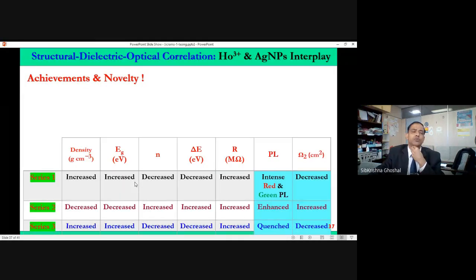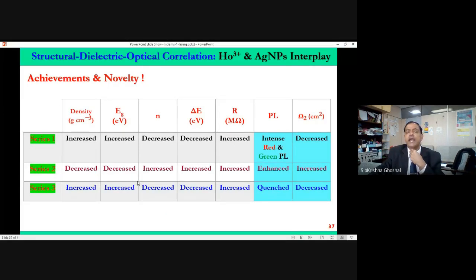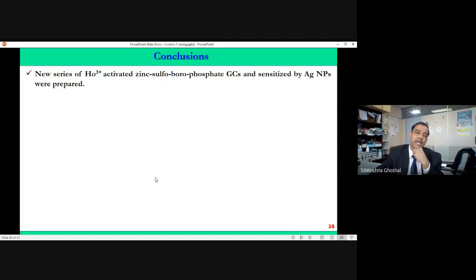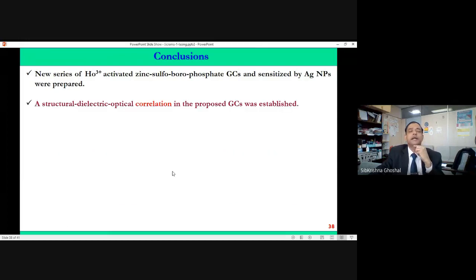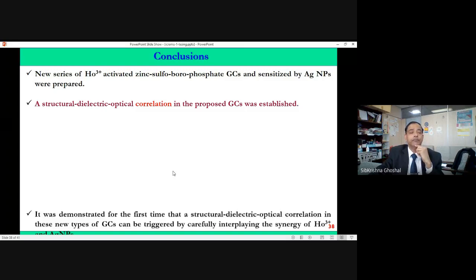So what is the novelty of this work? The novelty is intense red-green PL, and also the purity in the color chromaticity, and the branching ratio and the stimulated emission cross-section are very high. For the first time, we showed that by tuning the structure and dielectric properties, you can tune the entire lasing property of the system. So in conclusion, I would like to say the new series of holmium activated zinc sulfur borophosphate glass ceramics we successfully prepared, embedded with silver nanoparticles. And structural optical dielectric correlation we have shown for the first time.